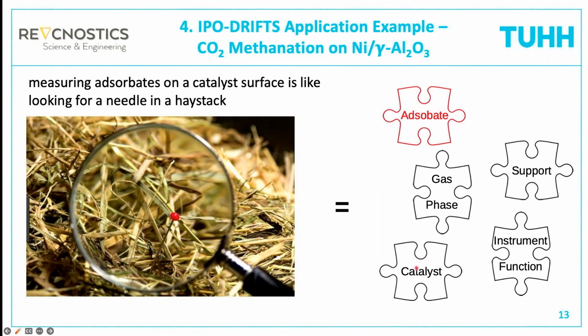If it's metallic nickel, then not, but if it's nickel oxide, then also the bulk catalyst would absorb the IR radiation. And then we have, of course, IR losses in the instrument, which also have to be accounted for. So we have an instrument function. And our approach now is that we want to measure the haystack with utmost accuracy and then subtract it so that the needle is left. This is the approach of isopotential operando DRIFTS.